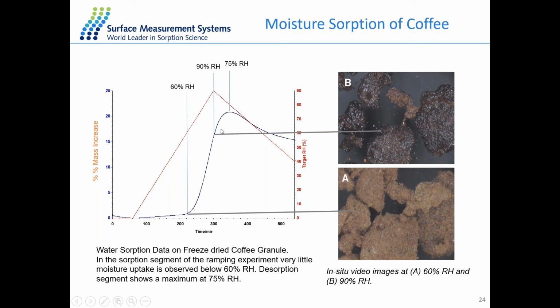And during the desorption step, the mass uptake keeps increasing and then reaches a maximum at 75% RH. So the deliquescence point is somewhere between 90% RH and 75% RH. And this is a stability mapping for the coffee granule, and we can perform similar experiments for other samples as well to study stability at different humidity at a certain temperature.